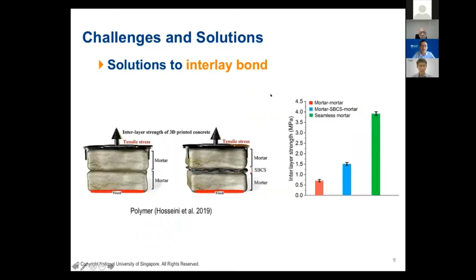In addition to the mechanical improvement, some researchers at Monash University are trying to put polymer in between the layers. So they put some polymer to increase the tensile strength. The direct tensile strength is measured. You can find this red color column is the direct tensile strength without anything. This is the cold joint, so the strength is very low. However, if they put some polymer, and the polymer can have interactions with the upper and lower concrete, so the tensile strength can be tripled. This is a very remarkable increase. Okay, so these are the main research efforts to increase the interlayer bond.